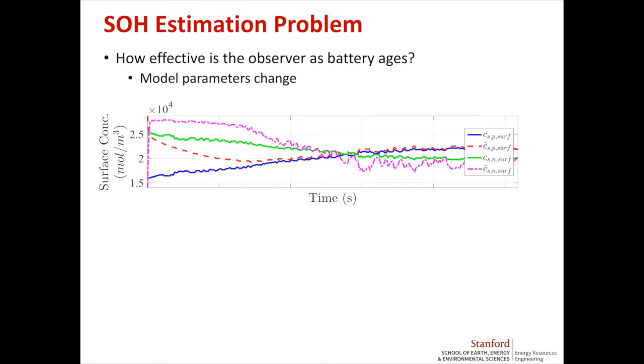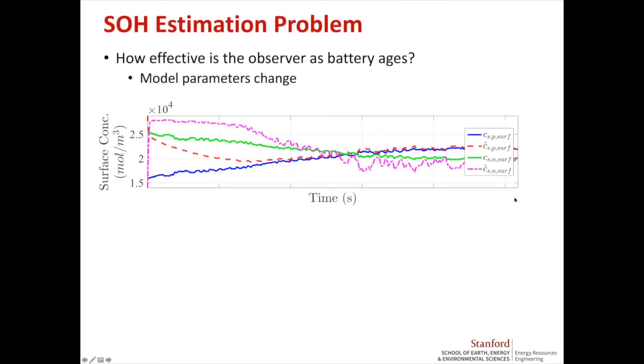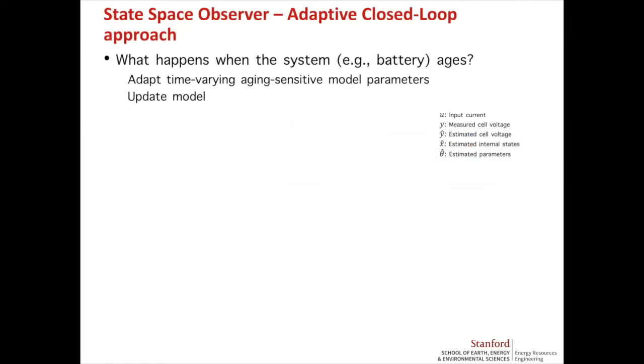As the battery ages, the parameters of the model change as well. So if you try to use that estimator I showed for an aged battery, there is no convergence. The surface concentration of lithium does something completely different from the real one. So you need to make some changes to that framework and equip it with some adaptation mechanism. You need to be able to adapt some key parameters that change with aging, which will basically advise your system about what's going on.